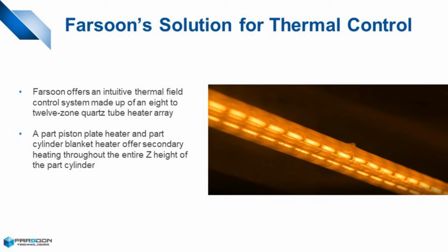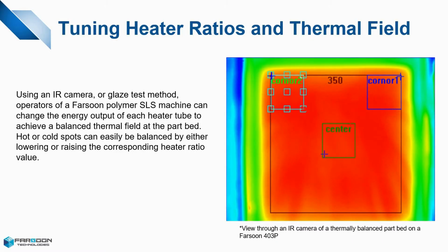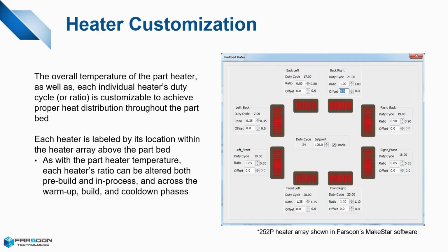Farsoon offers an intuitive thermal field control system made up of an 8 to 12 zone quartz tube heater array. A part piston plate heater and part cylinder blanket heater offer secondary heating throughout the entire Z height of the part cylinder. Using an IR camera or glaze test method, operators of a Farsoon polymer SLS machine can change the energy output of each heater tube to achieve a balanced thermal field at the part bed. Hot or cold spots can easily be balanced by either lowering or raising the corresponding heater ratio value. The overall temperature of the part heater, as well as each individual heater's duty cycle or ratio, is customizable to achieve proper heat distribution throughout the part bed.